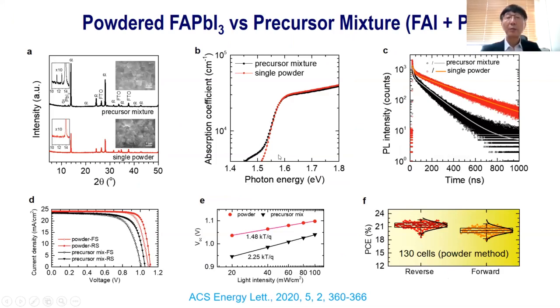the defects are pretty much removed, and carrier lifetime is pretty much increased as compared to the precursor mixture method, and also the ideality factor is close to the ideal device structure formed by the powder method. And then there is still a little bit of hysteresis.